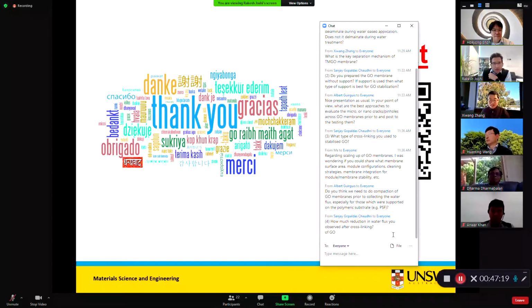And there was another question: do you prepare the graphene oxide membrane without a support? If support is used, we always use a PVDF support. We can make it without a support also, as you can see in Rahul Nair's 2012 Science paper. They were also not membrane people before, so they coated graphene oxide on copper and then etched away the copper using acid, but we always use it on a support.